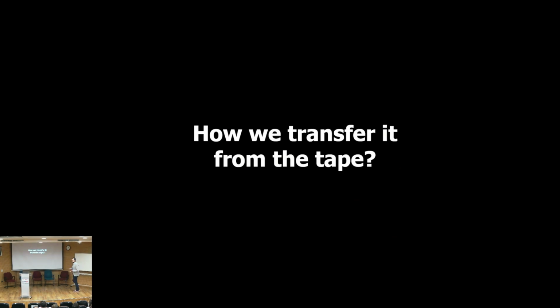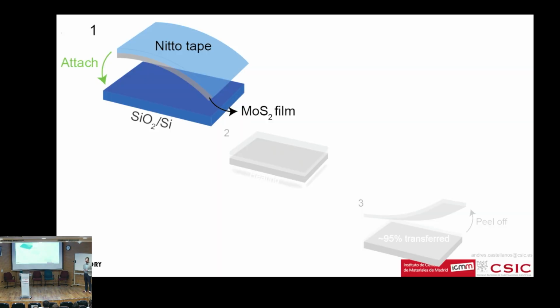But if it's on the tape, it's useless. So we have to find a way to transfer these crystals out of the tape and into our devices. That is what we want to do. And there is a very simple method, actually. It's a thermal release transfer. Nicely enough, this Nitto tape, if we heat it up to 100 degrees, loses all the tack, all the adhesiveness. Then we take the tape containing the film that we exfoliated.